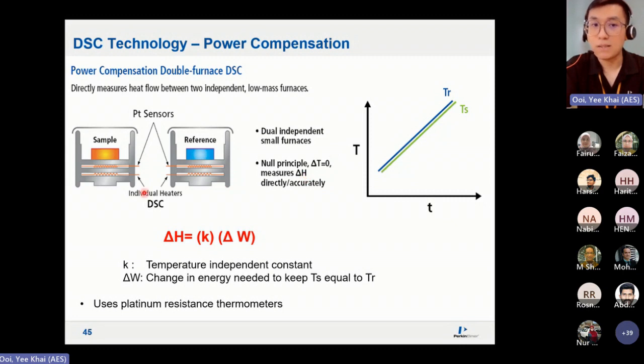And how much power is being supplied or withdrawn directly translates to delta H, meaning there is no conversion. Because of the power being supplied, you can directly measure how much is the enthalpy or the work being done. So there are no conversions. This is especially good for weak transitions, for example like TG, if you want to monitor that, or highly crystalline material where you want to measure how much is the amorphous part of the material. So this technique will be the best. This is Perkin Elmer's patented technology. Hence it's called power compensation, because it directly measures how much power is being supplied or withdrawn by the heater to maintain the same temperature as the reference temperature.